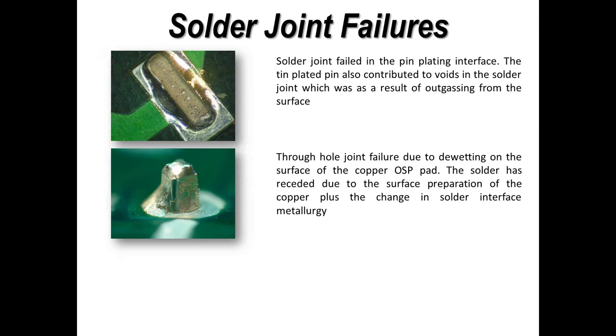And this is very, very similar to one that was sent into the NPL defect database only a couple of weeks ago. And I apologize to the engineer, I was on holiday, so I didn't respond quite as quickly as I would have normally done. But it's exactly the same. We've got a reflow solder joint. And what has probably happened most commonly with this type of failure, when it visually looks like this, it's a problem with the plating on the component. So it's not actually the solder joint per se, which is the problem, or the solder paste or the profile. So look at the component surface. That's probably what the root cause was. I know it was in this particular case, but it may well be on the example that I was shown.